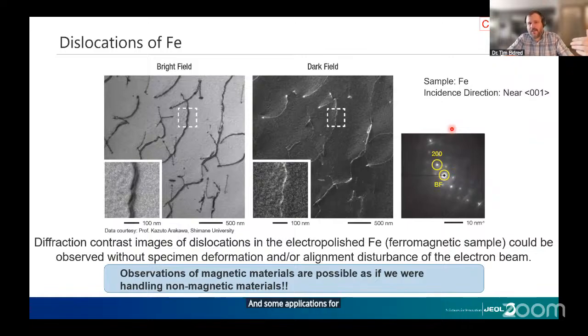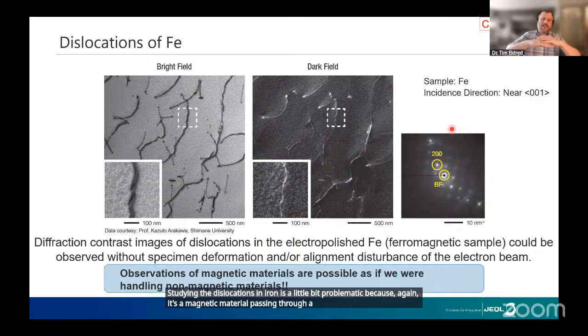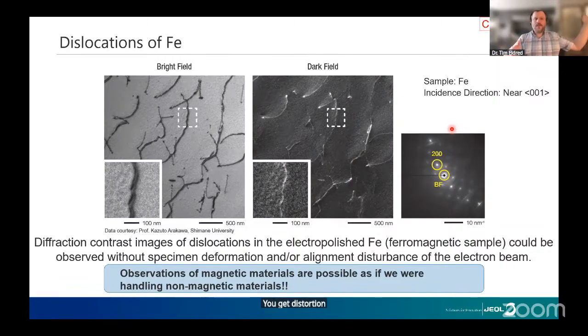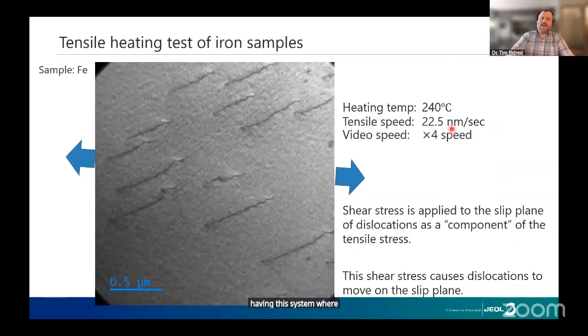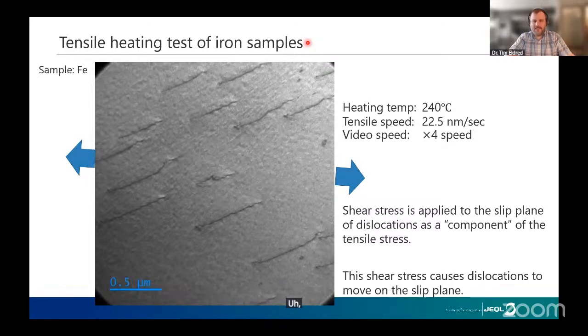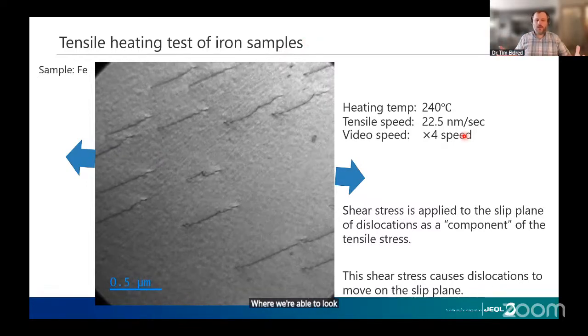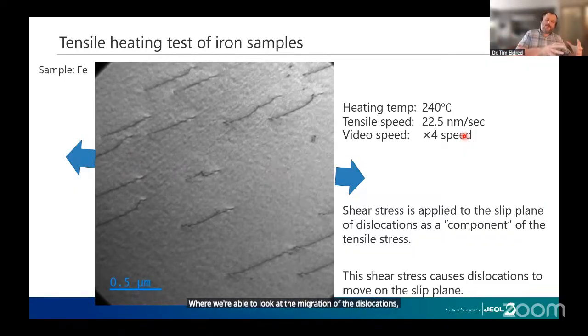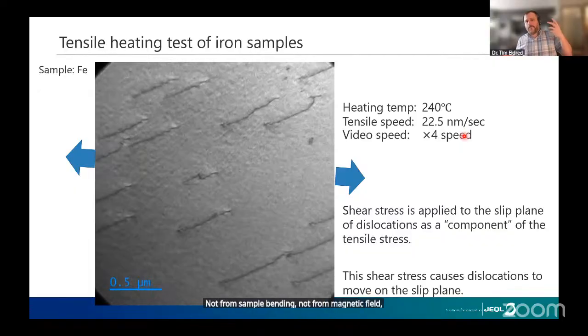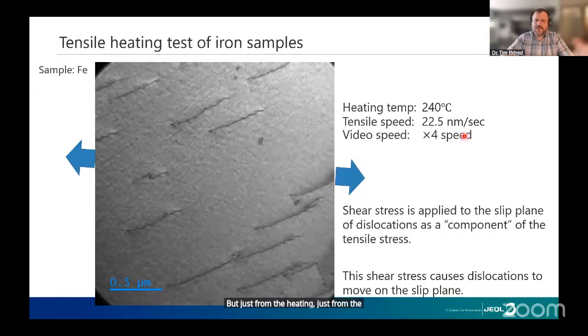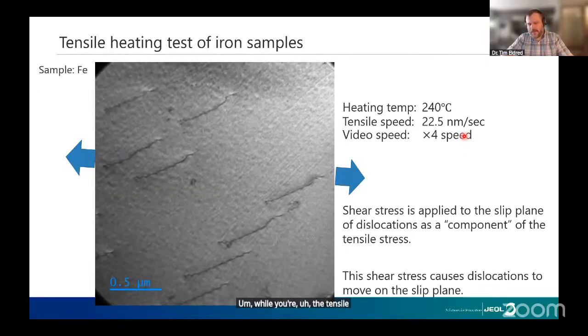And some applications for this: iron, a very common structural material. Studying the dislocations in iron is a little bit problematic because, again, it's a magnetic material passing through a magnetic lens. You get distortion. Distortion causes dislocation migration. And so it's difficult to tell whether what you're seeing is how it originally was or what has happened from movement. Having this system where we do not have a magnetic field has allowed us to do heating tests on iron, where we're able to look at the migration of the dislocations, not from sample bending, not from magnetic field, but just from the heating, just from the tensile stress while the sample is being heated.